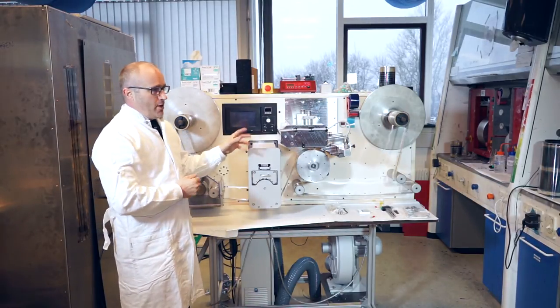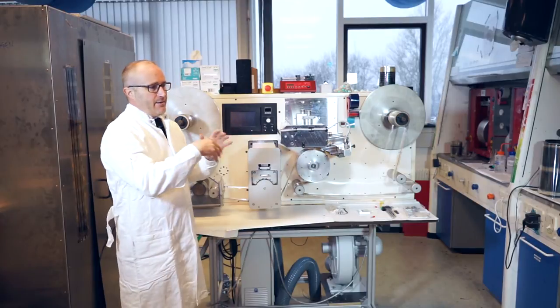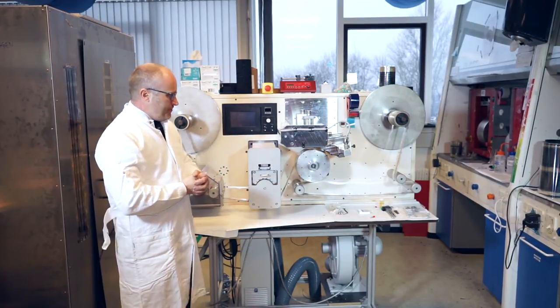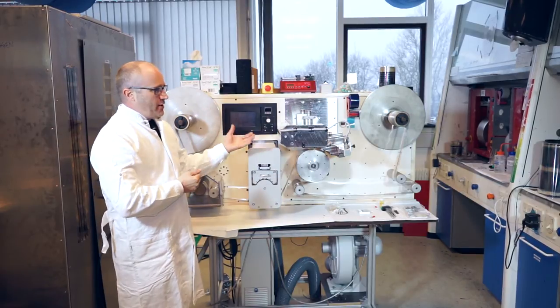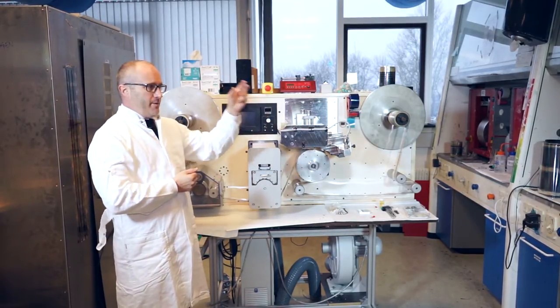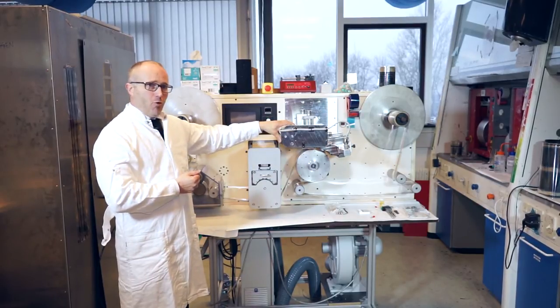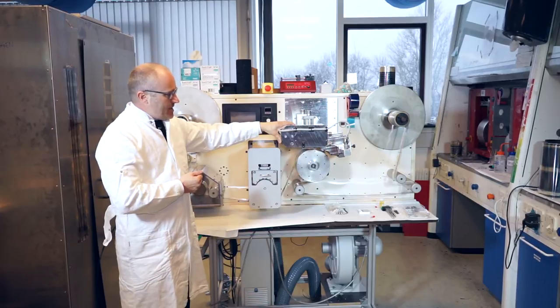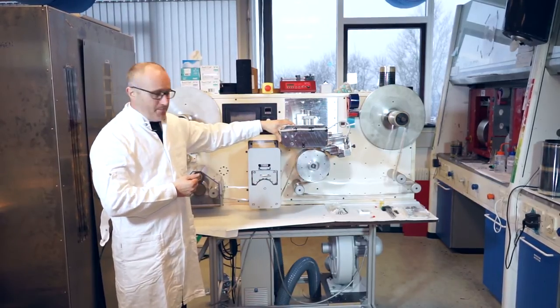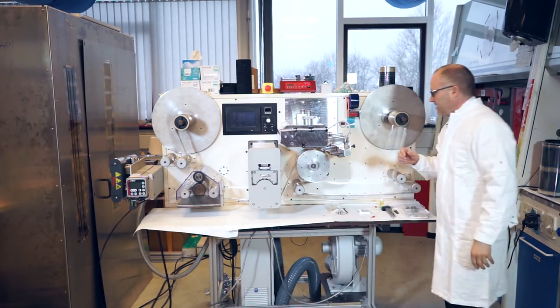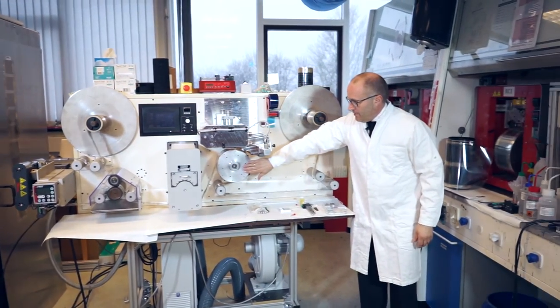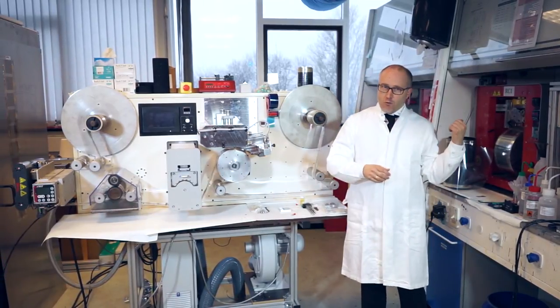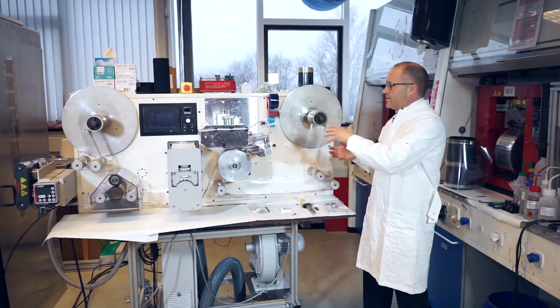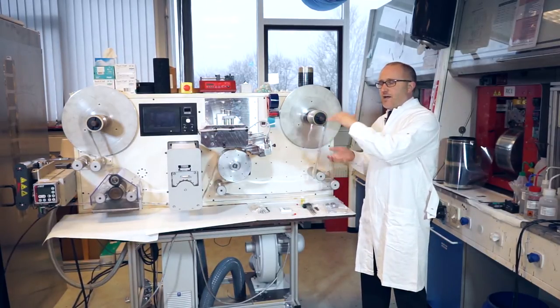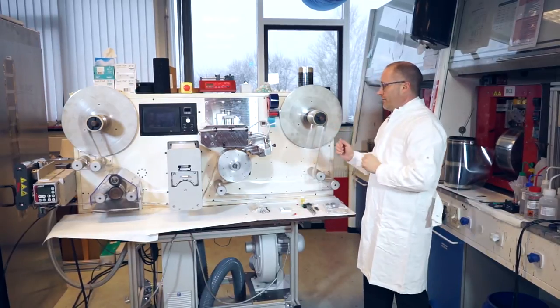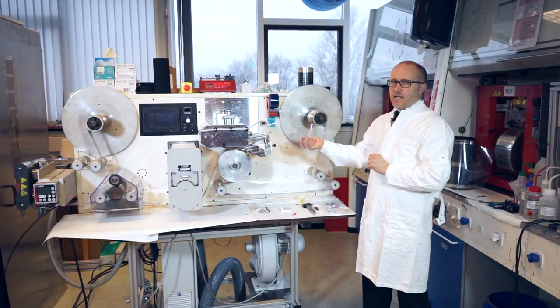The slot die coating head I showed earlier, the small mini slot die coating head, is exactly the same in principle and also in operation as on the mini roll coater. And so from that point of view, there is no real change in moving from the mini roll coater to this small roll-to-roll machine, except of course with the static fields that I mentioned. If I just move over here on the other side, we also have a heated drum here, significantly smaller than on a mini roll coater, but it's just to enable the control or eliminate the effect of the static field while scaling up. And this is, of course, needed in this scaling step.